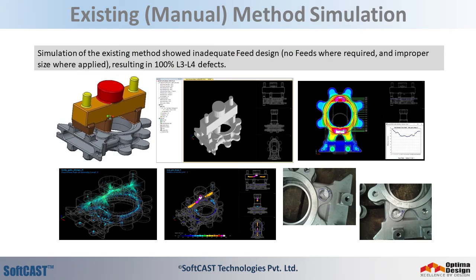The existing method for the knife edge valve body at this investment casting foundry did not assure quality at all, leading to 100% defectives. Simulation of the existing method showed inadequate feed, that is gate design. Feeds were not applied at the locations required. And at the incorrect locations where they were applied, they were incorrectly sized. All this resulted in 100% level 3, level 4 defects.